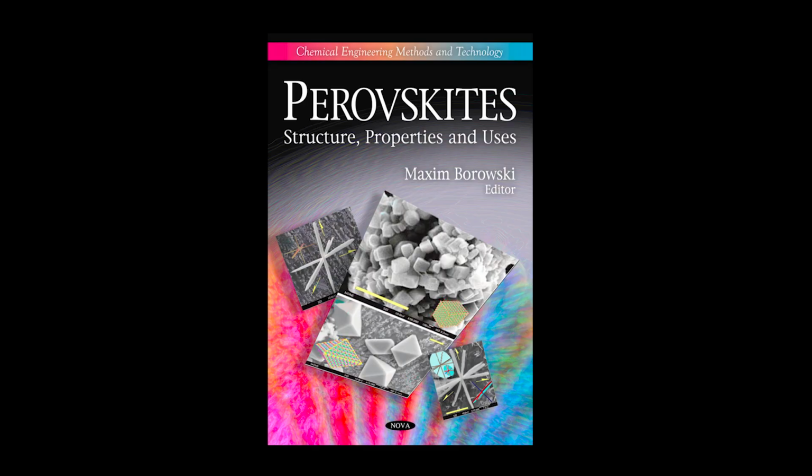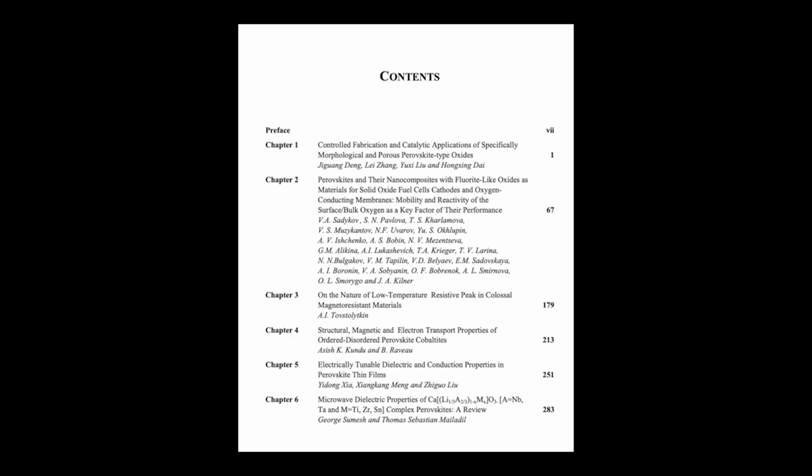So the peak isn't really a fundamental bulk phase transition itself, but rather a macroscopic performance anomaly dictated by the degree of disorder, the connectivity of the FM phase, and the interface resistance between the FM and PM regions in that specific inhomogeneous sample. That's a really neat synthesis. The material's failure to be perfectly uniform is actually what creates its unique and initially confusing electrical signature.